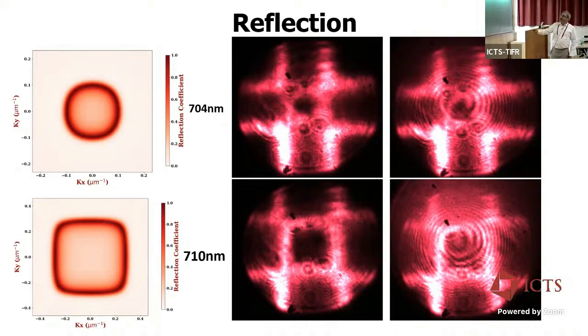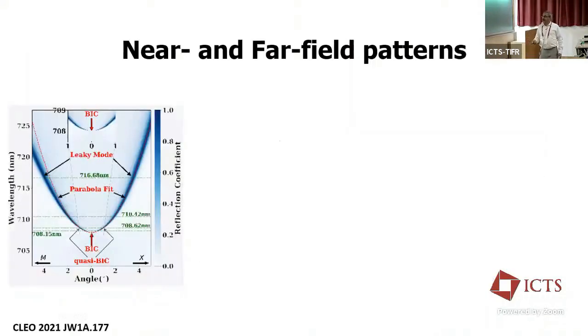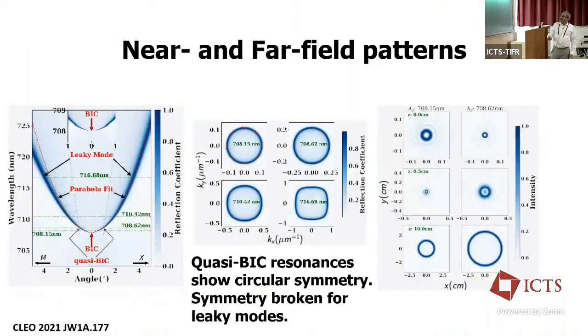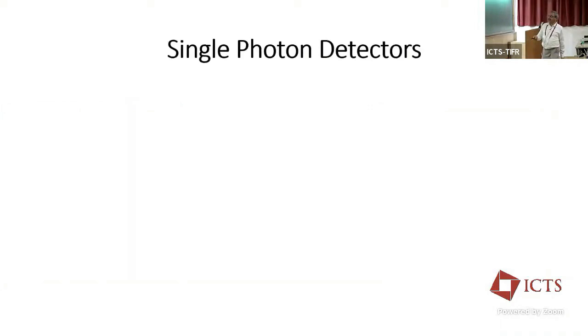Right? So this is one way to check whether at resonance we have spherical symmetry or circular symmetry, and if we move away from resonance, in the far field we see this reflected spot show this square pattern. Right? So, as I mentioned, the near field profiles show this vectorial nature. You have the interference patterns which are seen in the near fields. Right? So the other work which we do is on single photon detectors.